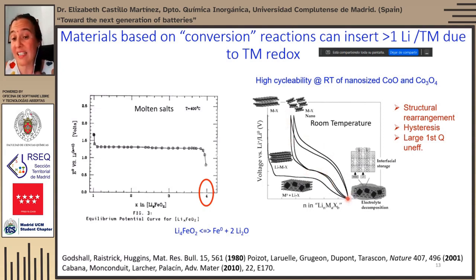And this is because the structure that is cycled in the first cycle is different from that of the following cycles. Indeed, during the first discharge, what is proposed is that metal nanoparticles are formed within a matrix of the oxide or nitride or sulfide of lithium, and with also some phases from the electrolyte decomposition. Moreover, there is some additional capacity to that expected for the insertion of 1 or 2 or 3 lithium ions.